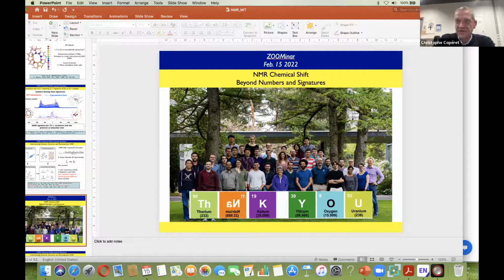So we have not looked so much at phosphorus, much more at N15. What I really like is pyridine, because pyridine is a pi system, there is a very strong coupling between the sigma lone pair and the pi star. So anything which is sp2 is very, very sensitive to anisotropy, similar to sp3 to sp, but sp3 is less sensitive to anisotropy. Now we are moving on, and we work a lot with Aaron Rossini and Lesage, more on platinum NMR. Some work related to what Autschbach has done a while back is to look at anisotropy in metals, where chemical shift anisotropy can be 5,000, 6,000 ppm. So I think there are a lot of things to do in metal NMR in that respect, and I know many people are looking at that.